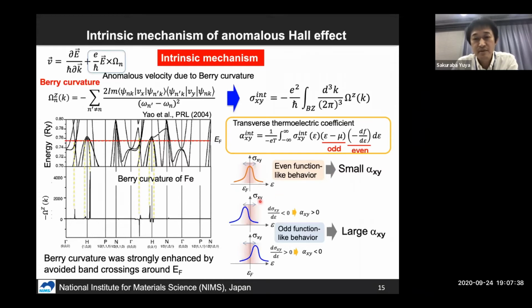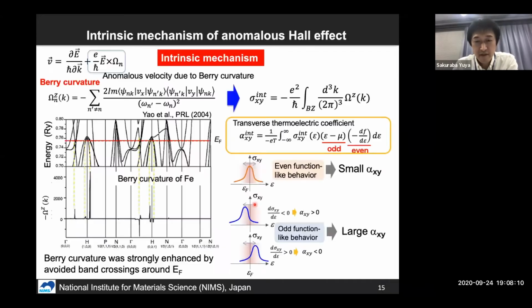But if sigma xy shows this kind of odd function-like behavior, we can expect an enhancement of alpha xy due to the contribution of the intrinsic anomalous Hall conductivity. So we should carefully look at the energy dependence of sigma xy around the Fermi level to search for materials having a high anomalous Nernst effect. Okay, so this is very important information.